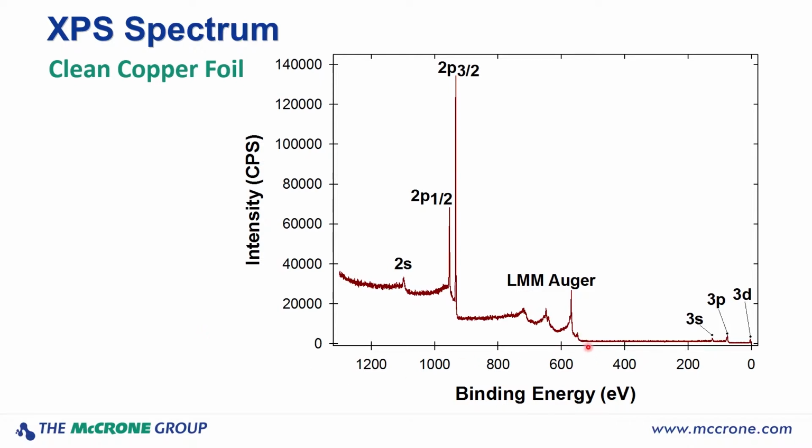And so if you look at the spectrum and you see these changes in background at various energies, those are actually photoelectrons that aren't being emitted with characteristic energies, but rather have been scattered inelastically in the sample, lost energy, and appear as just background signals. So only the photoelectrons being produced in those outer few atomic layers on a sample are able to escape and be analyzed by our spectrometer and appear as peaks in our spectrum.